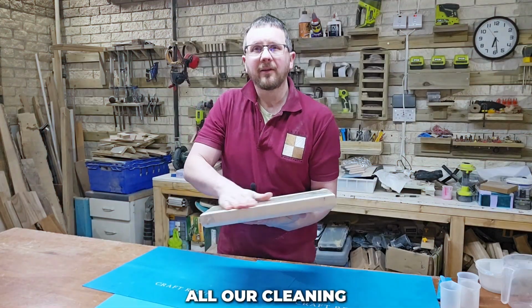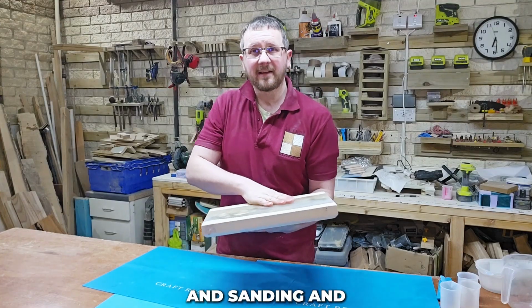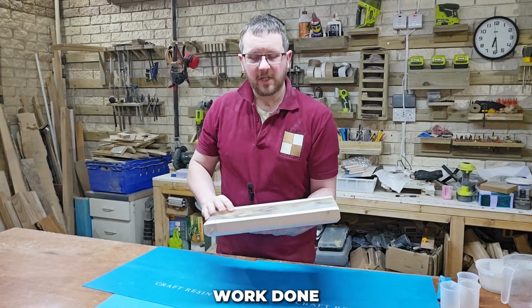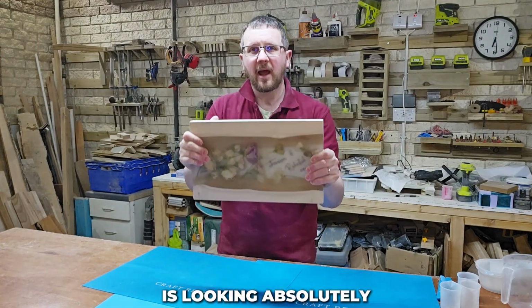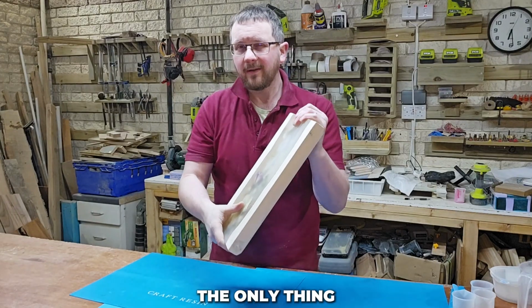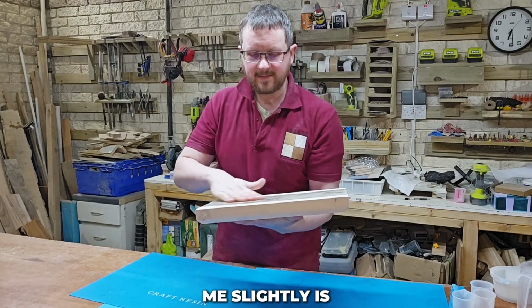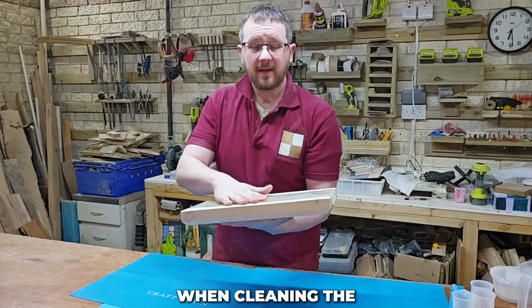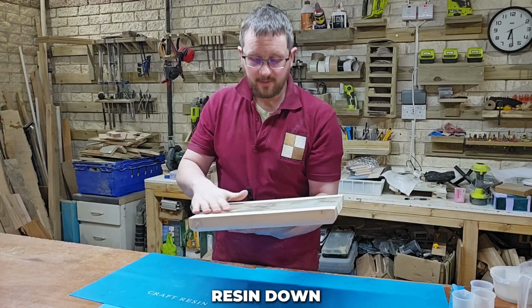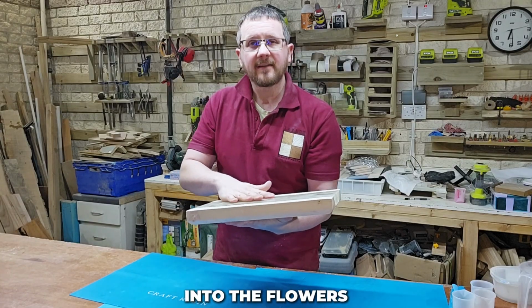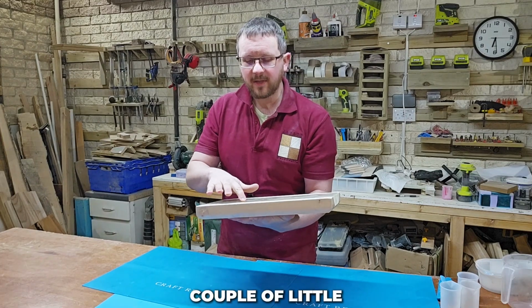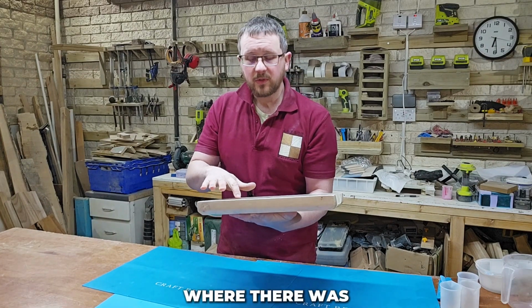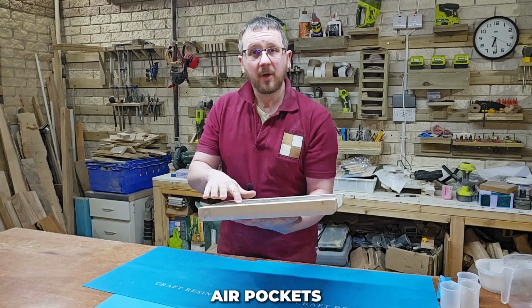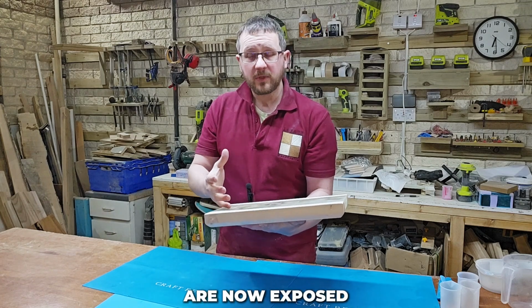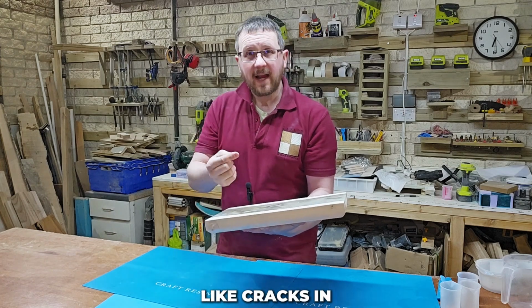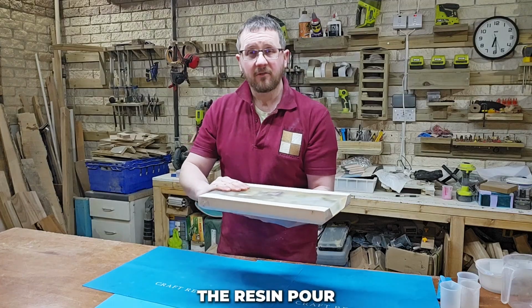So we have all our cleaning and sanding and all the dusty work done, and the board is looking absolutely fabulous. The only thing that has annoyed me slightly is that when cleaning the top of the resin down, I've actually nicked into the flowers, and you can see there's a couple of little areas where there was no resin and there would have been air pockets, and those areas are now exposed, so they're leaving little cracks in the resin pour.